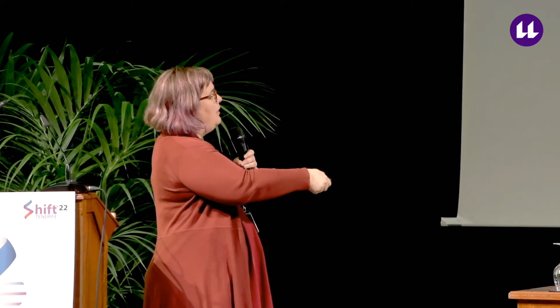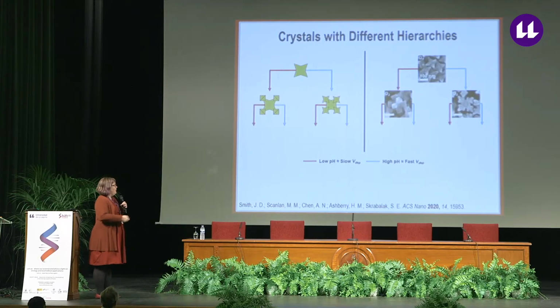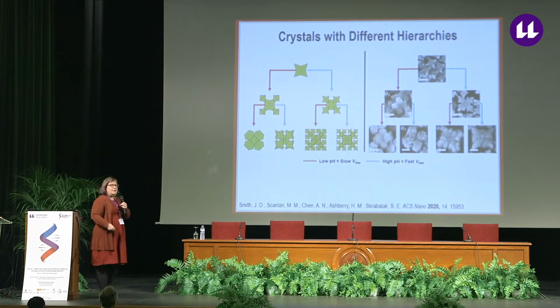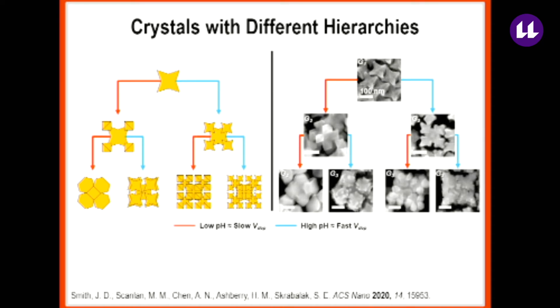But we have options on how we do the deposition. We could, for example, select low pH conditions where the rate of deposition is slow relative to diffusion of the add atoms. That favors more polyhedral nanocrystals. Or we could select higher pH where metal deposition will be fast relative to add atom diffusion. That favors more branching. And so, as anticipated, we end up now under the slow conditions with polyhedral tipped octopods, whereas on the right, we have additional branching where the branches are proceeding along the 1-1-1 directions. We can then take these seeds and use them again, considering different deposition processes, and build up crystals with different hierarchies.